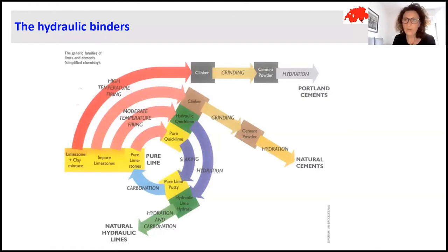Between these two materials, we also have, how can I say, hybrid materials. So materials that have an air hardening part and also a hydraulic part. And this is especially the case of historic mortars. Here we see in this scheme, the more impure the raw material is, with clay content, the more hydraulic the mortar I will obtain. The more clay content, the higher the temperature I need to reach within the kilns.